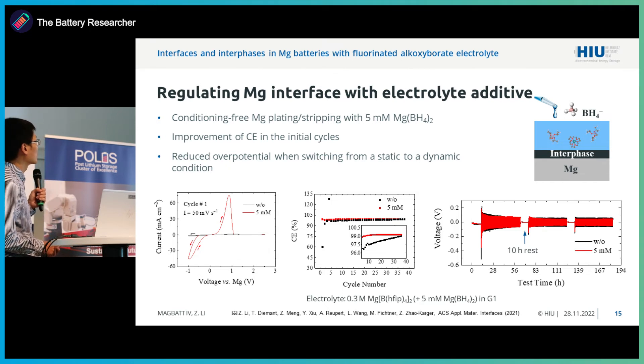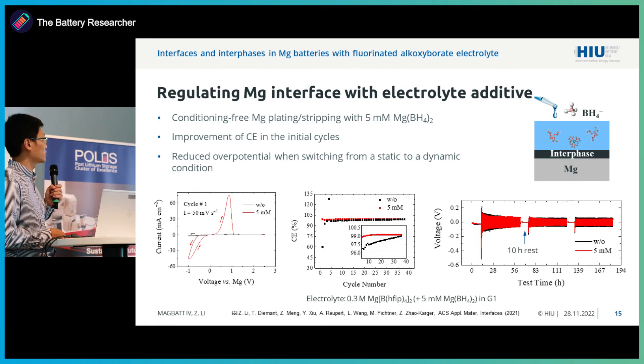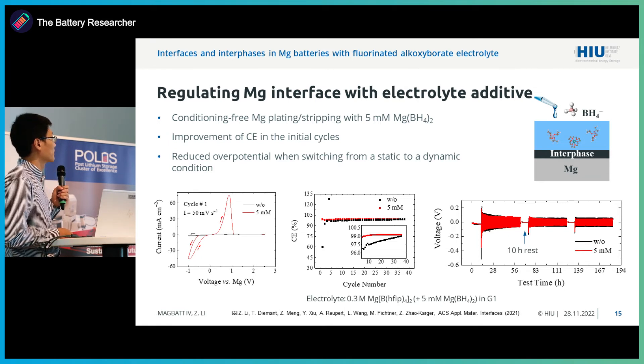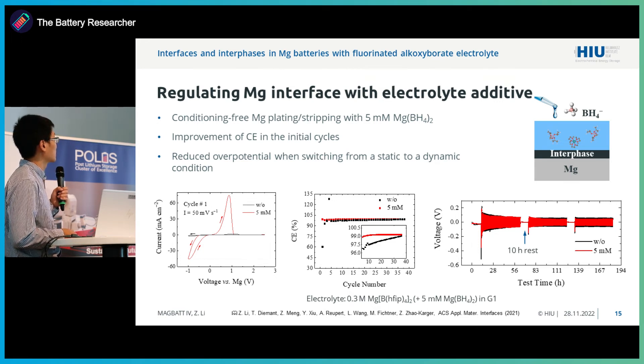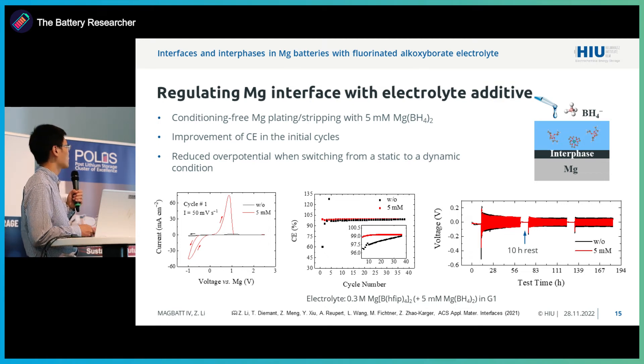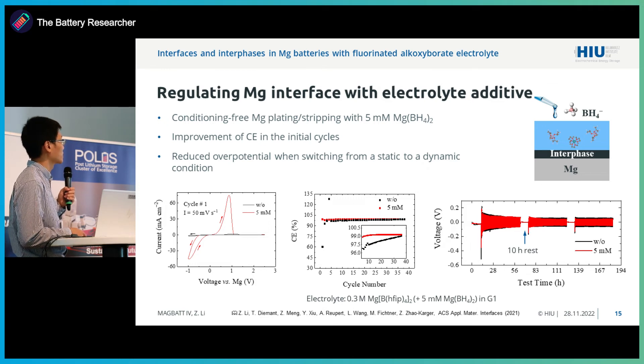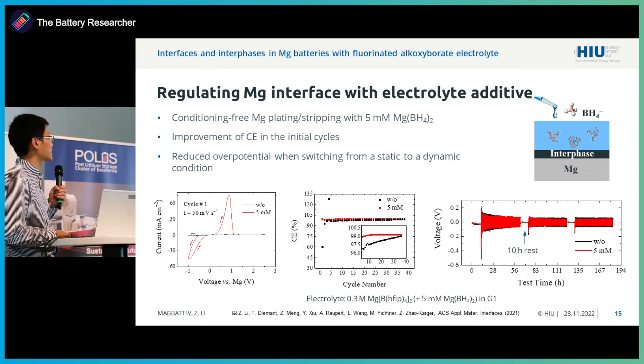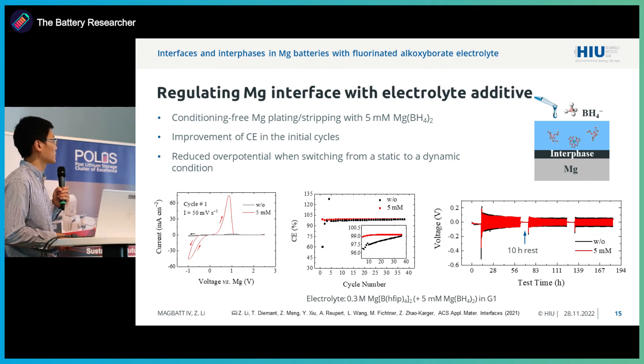This also leads to a reduction of the overpotential in the symmetric cell. We also tested by switching from static to dynamic conditions — stopping the cell in between and restarting it at certain points — and we see that all the overpotentials decrease if we have the additive present.